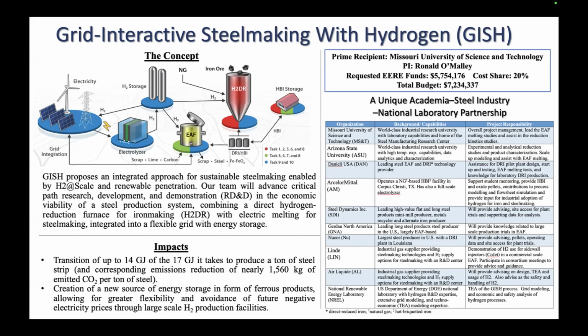So the whole concept here is that we can produce materials that are required as virgin iron units for the EAF as needed through natural gas, but take advantage of the availability of low-cost hydrogen when it is generated at off-peak periods. And this program has many partners in it and actually has many parts to the program to try to understand the knowledge gaps associated with not only the production of DRI in hydrogen and natural gas swing reactions, but also in the utilization of hydrogen DRI with its absence of carbon in the electric furnace and the impact on melting behavior.